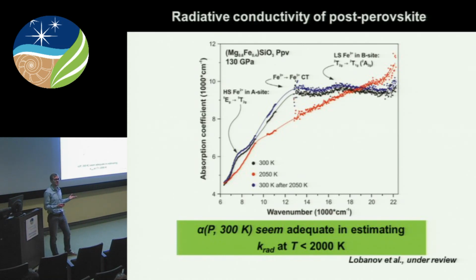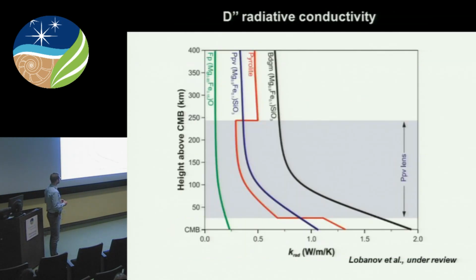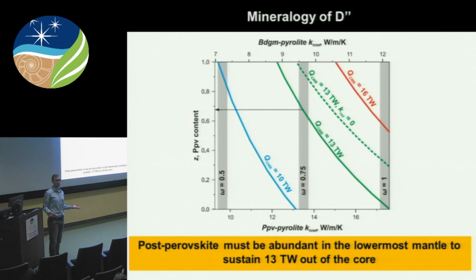Now we can do absorption measurements at high temperature. And here I'm showing you absorption spectra of post-perovskite before and after heating, the blue and black spectra. You can see that they are almost exactly the same. And the red spectrum is post-perovskite absorption at 2000 Kelvin. So we can see that there are some changes, but they're probably not very significant. And we can use this absorption spectrum to constrain radiative thermal conductivity at this pressure and temperature. The result tells us that room temperature measurements may be adequate in constraining radiative conductivity at temperatures below 2000 Kelvin.